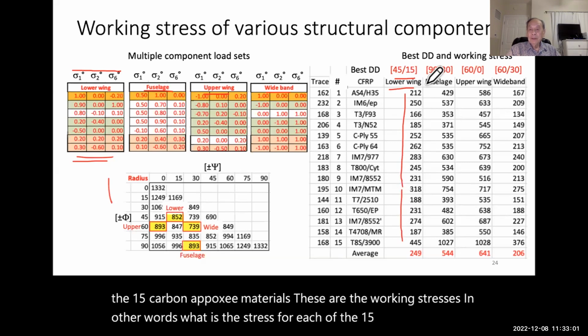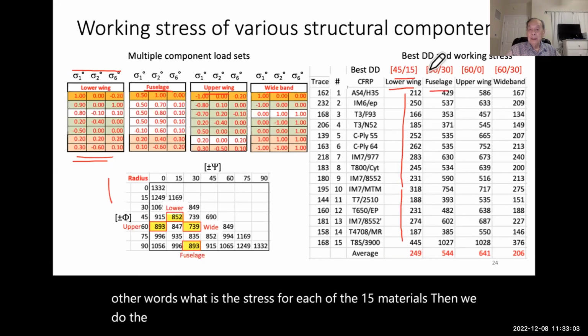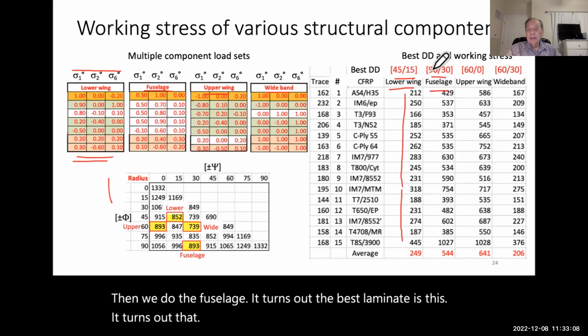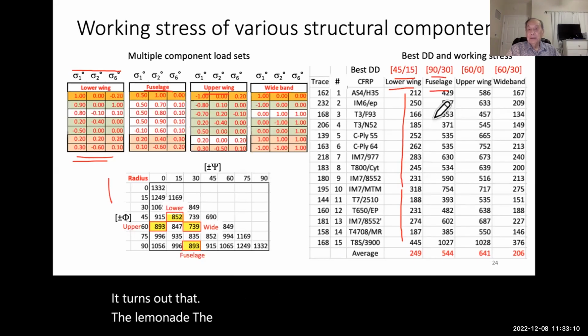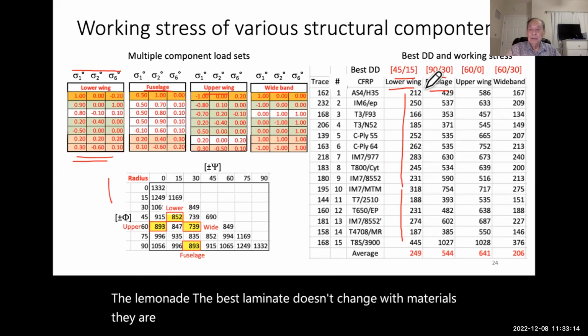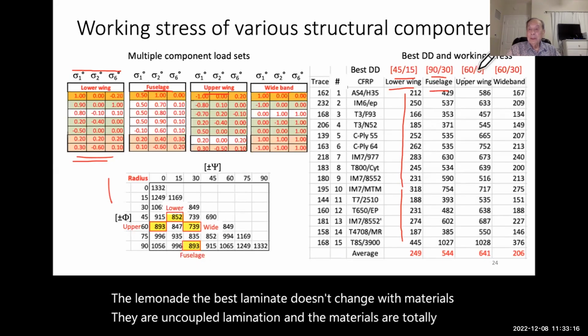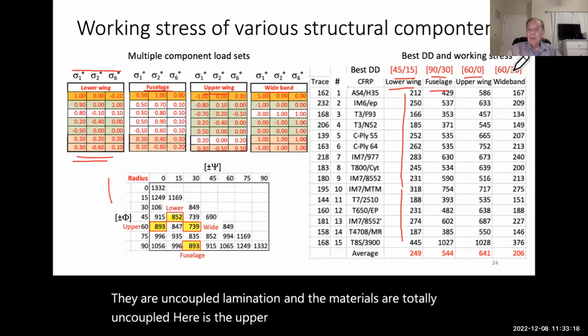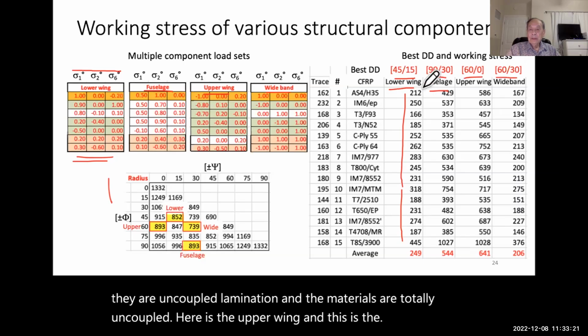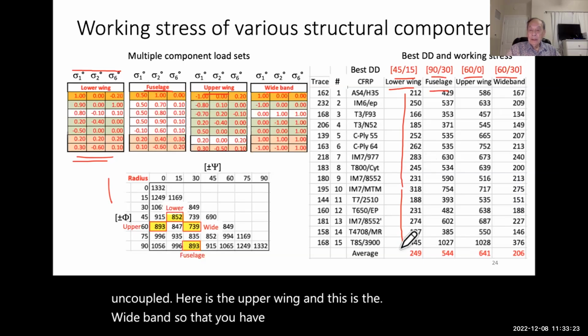Then we do the fuselage. It turns out the best laminate is this. It turns out that the best laminate doesn't change with materials. They are uncoupled. Lamination and the materials are totally uncoupled. Here is the upper wing, and this is the wideband. So that you have these values, then we can try to rank these materials.